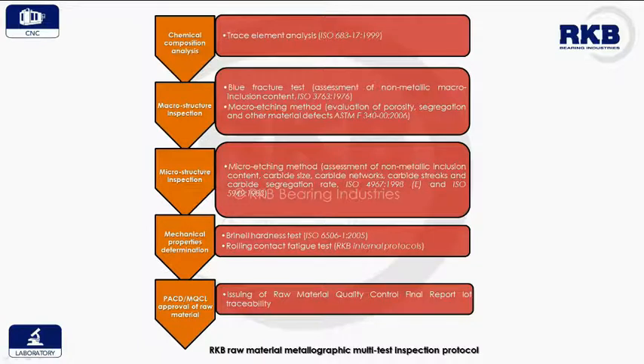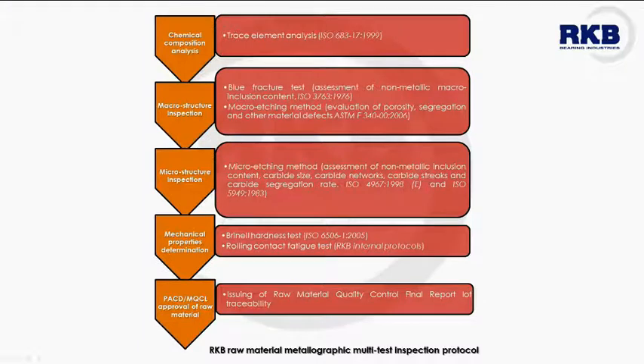The raw material quality control performed by RKB applies to both through-hardened and case-hardened steels and is based on multi-test inspections according to our material guidelines. These multi-test inspections strictly follow the applicable international standards and include raw material chemical composition analysis, macro and microstructure inspections, mechanical properties determination, and the raw material quality control final report issue for lot traceability. This final report is released by the metallographic quality control laboratory and the mechanical testing laboratory. They are part of the RKB product approval control department.